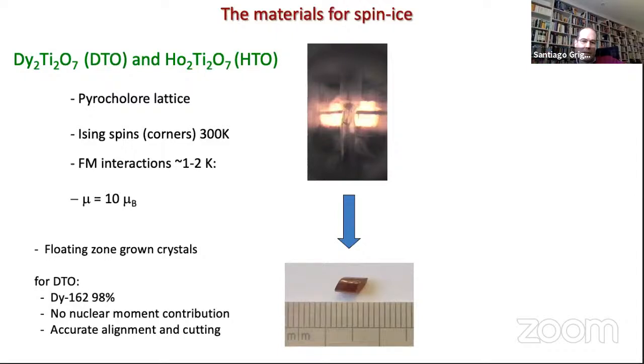Okay, as I said, this is an experimental talk. So we need to talk about materials. So essentially, we're going to be discussing 2 materials: the dysprosium titanate and holmium titanate. They have a nice pyrochlore lattice of the dysprosium or the holmium, which are the magnetic moments. Titanium is non-magnetic here. They're Ising type spins in the sense that because of the crystalline field, you need a temperature above 300 K to excite them away from the Ising states. And we're going to be working below a couple of Kelvin. So for all intents and purposes of our work, they're nice, well-behaved Ising type spins.